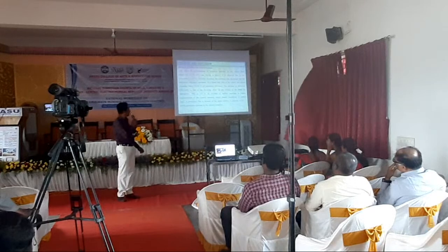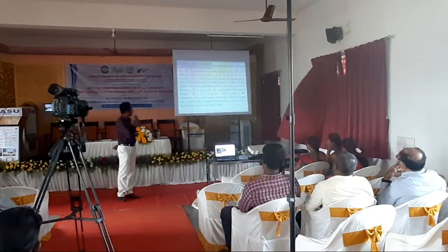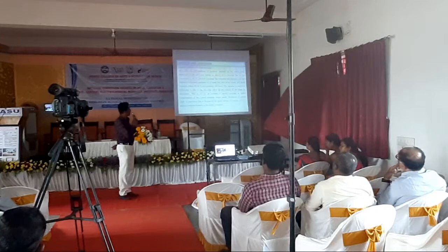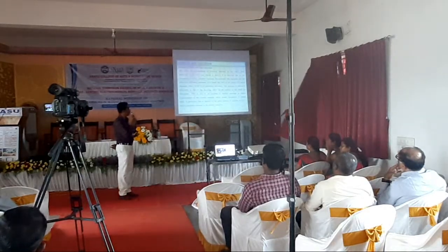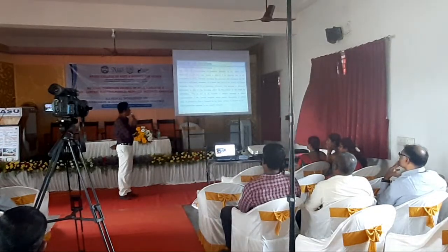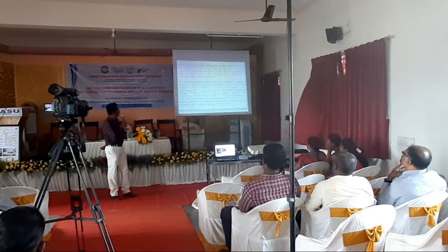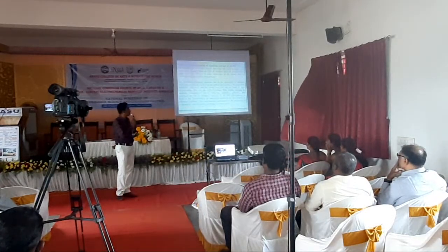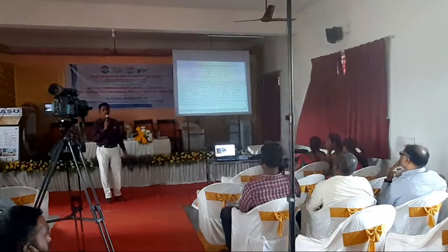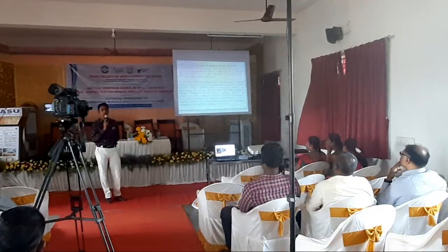The result and discussion: we add the inhibitor. It is found that 10% of the extract of Carissa carandas offers 90.33% inhibition efficiency. The increase in inhibition efficiency is due to the blocking effect on the surface of the metal by adsorption. This is due to an increase of surface coverage at higher concentration of Carissa carandas, which retards the dissolution of carbon steel. We add 2 ml, 4, 6, 8, 10 ml. Above 10 ml, there is no change in the corrosion inhibition efficiency.